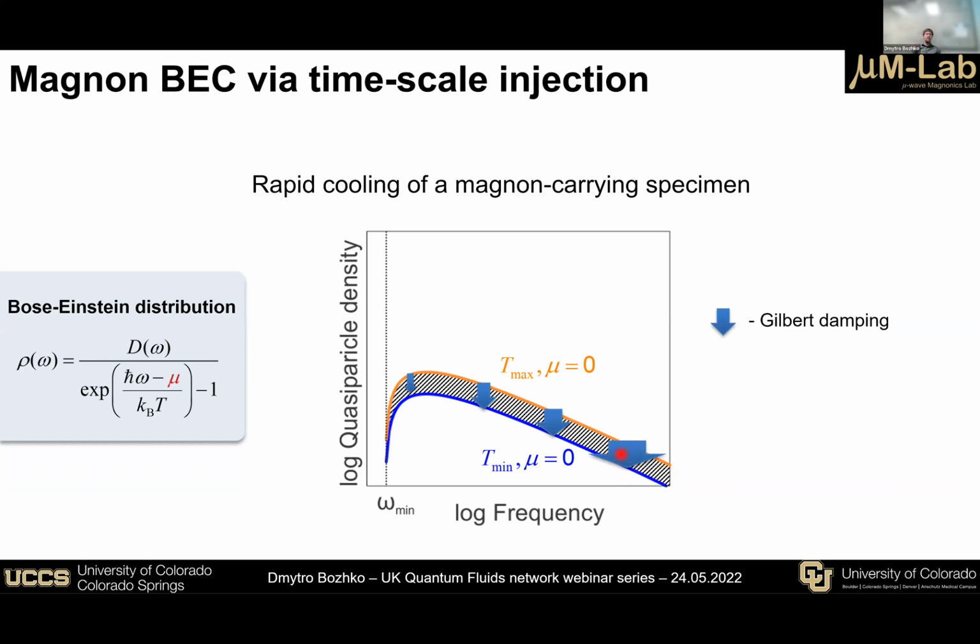They decay fast, but at the same time the scattering rate is also huge, because first of all, nonlinear four-magnon scattering is proportional to the frequency to the power 4. So these Cherenkov processes are kicking in. Yeah, it's a very efficient process.